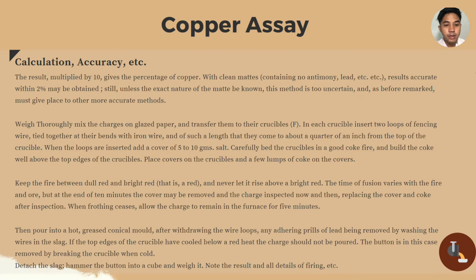So here we will be tackling the calculation and accuracy. The result multiplied by 10 gives the percentage of copper. With clean mattes containing no antimony, lead, etc., results accurate within 2% may be obtained, unless the exact nature of the matte be known. This method is too uncertain, and as before remarked, must give place to other more accurate methods.